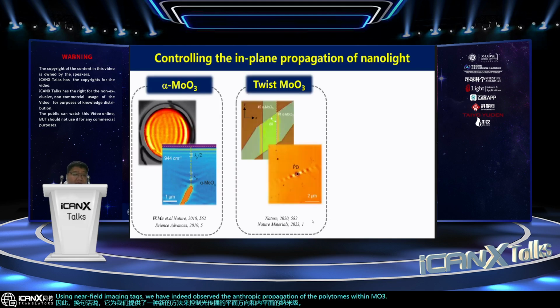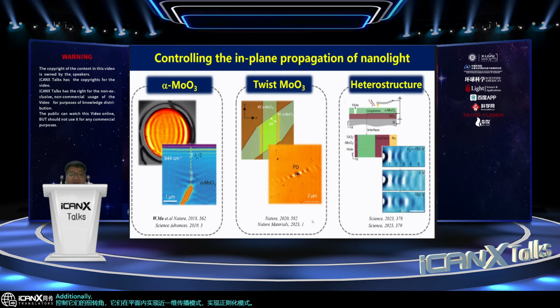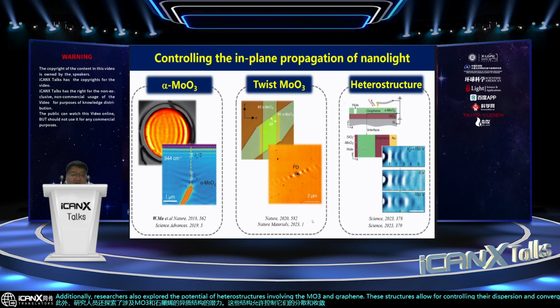Subsequently, by employing bilayer MoO3 structures with controlled twisted angles, they achieve near one-dimensional propagation patterns within the plane, enabling canalization mode. Additionally, researchers also explored the potential of heterostructures involving MoO3 and graphene. These structures allow for controlling the dispersion and convergence characteristics of the polaritons within the plane using the gate voltage, leading to in-plane negative reflection effects.